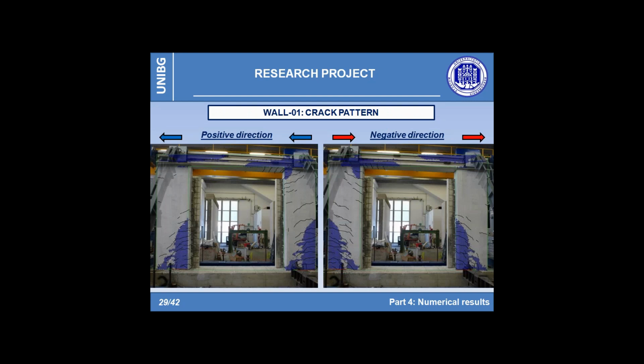Trying to compare the crack layout observed during the test with that provided by the numerical analysis, in this slide the cracks that appear during the application of the load only in positive direction and in negative direction have been distinguished. In particular, in the left image, the load is applied in positive direction, from right to left, as also deducible watching the orientation and the localization of the cracks. On the contrary, the picture on the right side shows what has happened during the application of the displacement in the negative direction. The picture highlights the superimposition between the experimental cracks, black lines, and the cracked area caught numerically.